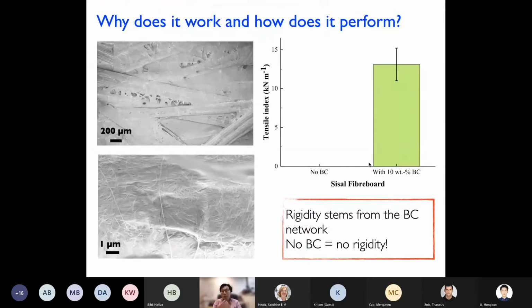And if you were to look closely at its morphology, you can actually look at the sisal fibers there. Those are the bigger fibers that you see. And these are the bacterial cellulose network. So they are not your 50 nanometer, but they're 50 nanometer agglomerated together, forming that network that you see. You can regard them as your mini nanopaper, if you will.